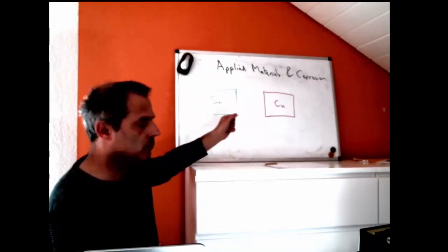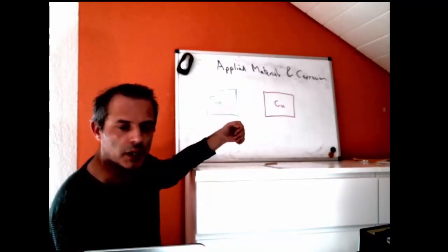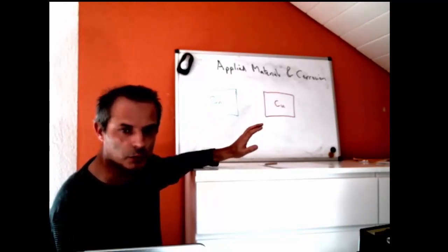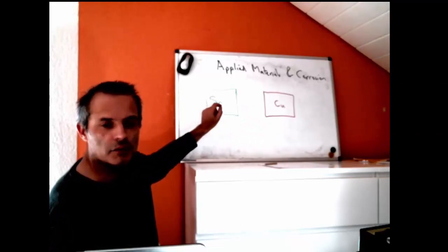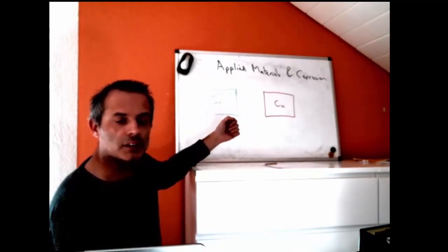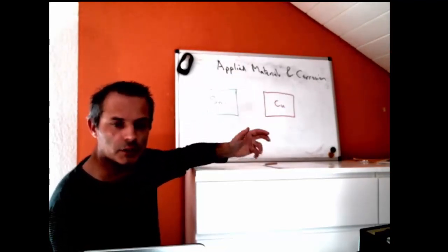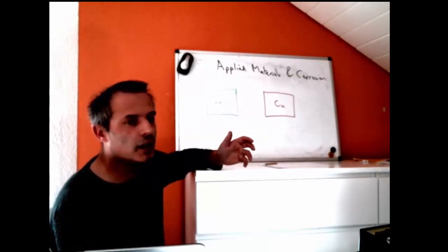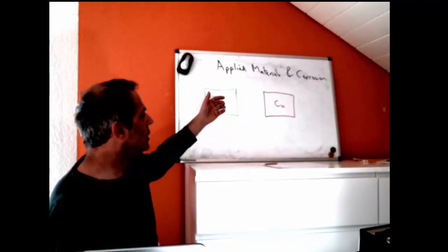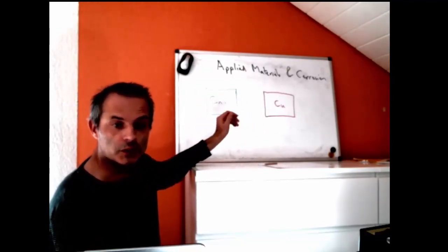dissolving in mild acid is strong enough, so the reaction is negative enough that it could cause hydrogen to form. However, the overpotential of hydrogen on tin is quite high, and so it is very slow and doesn't happen very much at all. So we take a piece of tin and throw it into hydrochloric acid and nothing happens. The tin is reasonably stable because the hydrogen can't form on the surface of the tin because of the activation